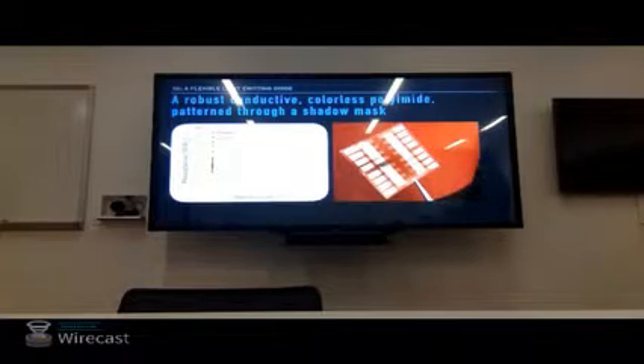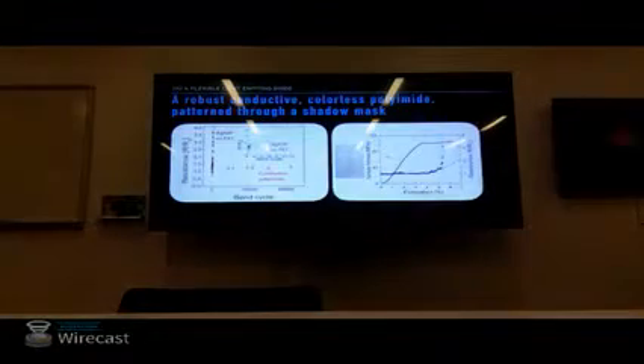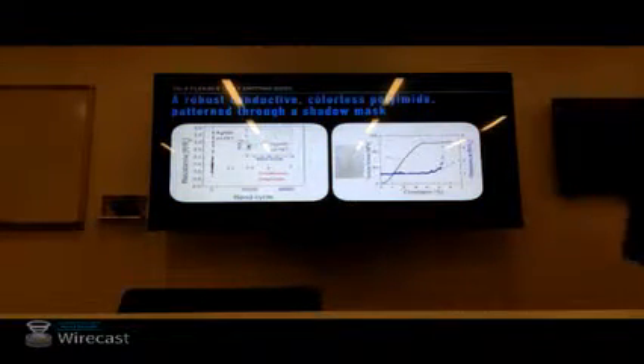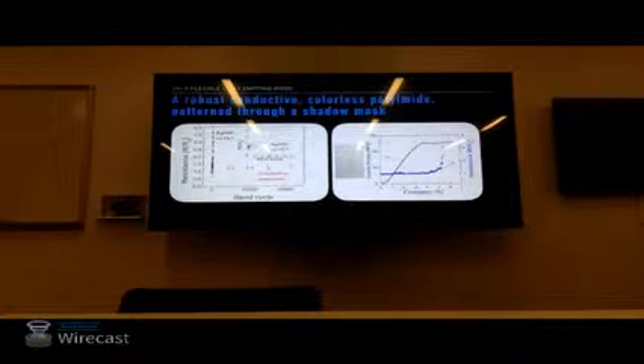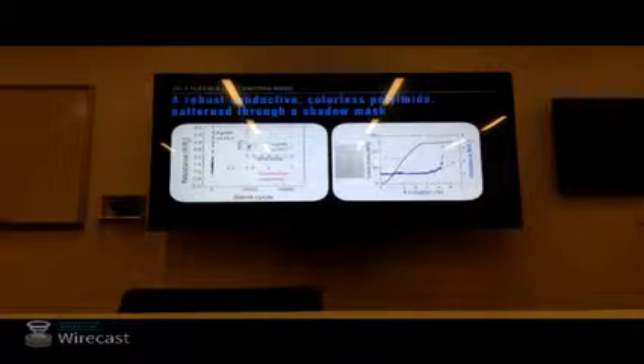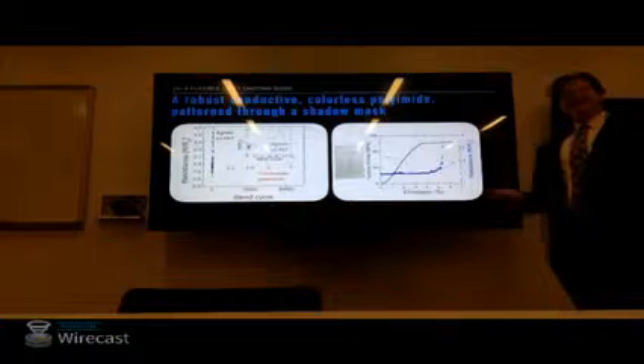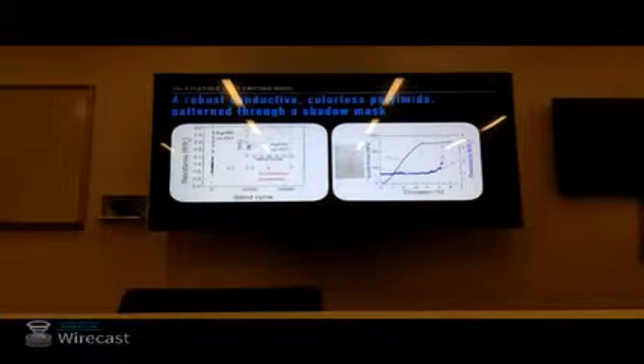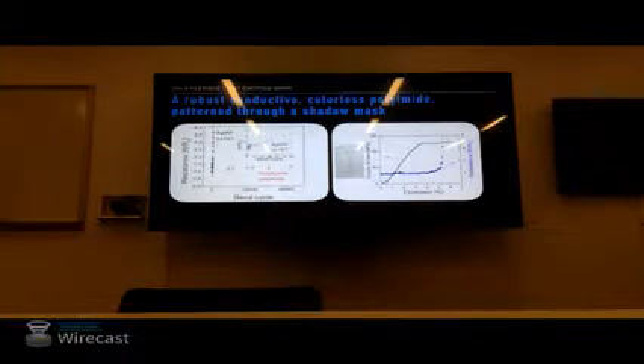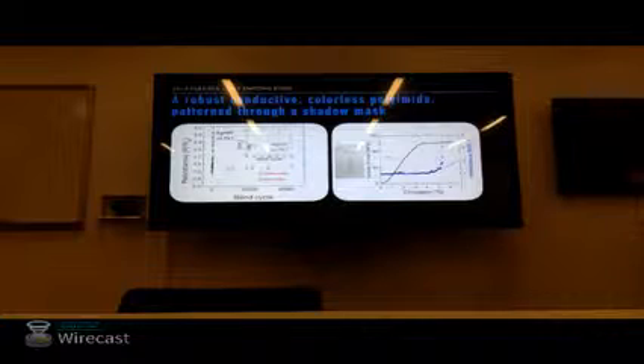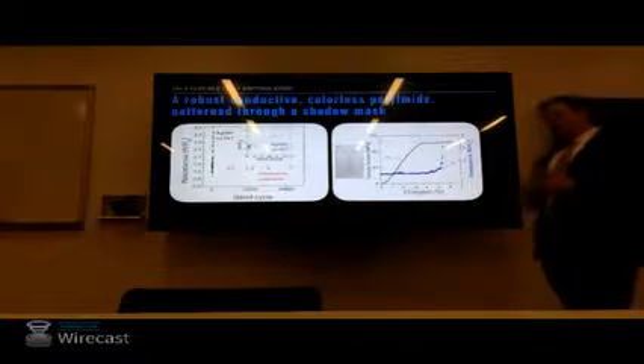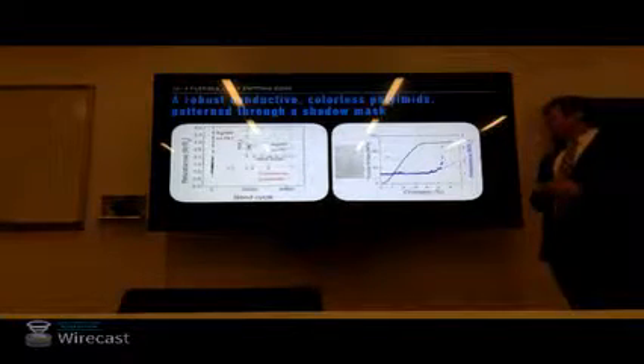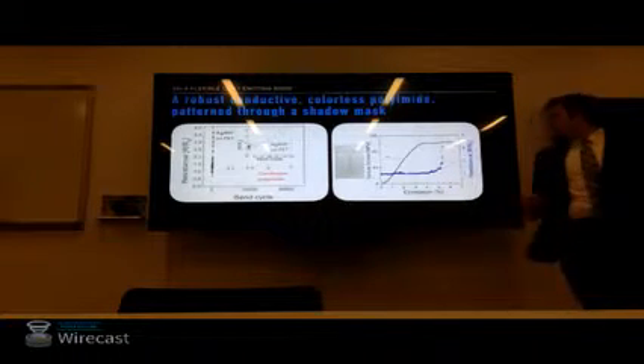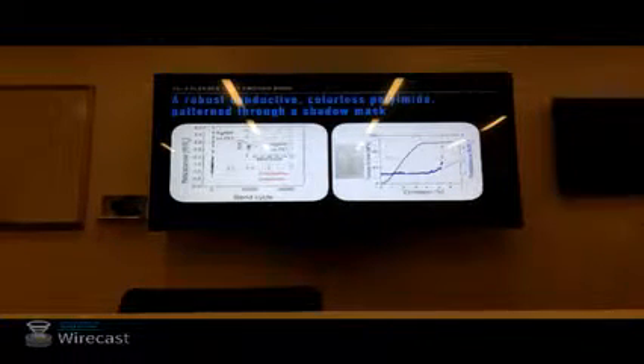So much better. I also have access to an Instron machine, so why not make a dog bone of this material and pull it apart? And we can show what we found, that they're not very stretchable. I can get an elongation of about 5%, but because we have a percolative network, which is mediating our conduction, the resistance starts going off even before failure.